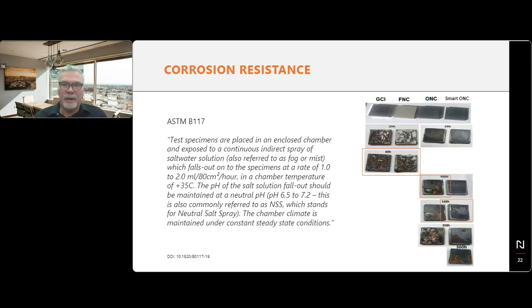Now, one of the last corrosion tests that we have done, and this is very interesting, is okay. One disclaimer here: typically, for vehicles, this test does not really represent working conditions. This is a standard salt spray test, which is common in metallurgy, but vehicles are subject to different media pollution. So there are eventually alkaline attacks, caustic or acidic attacks on the brakes. So this is completely neutral, and therefore not completely duplicating real working conditions. However, you can use this test just to assess the different reactions of different surface finishes to corrosion. It still is a baseline.